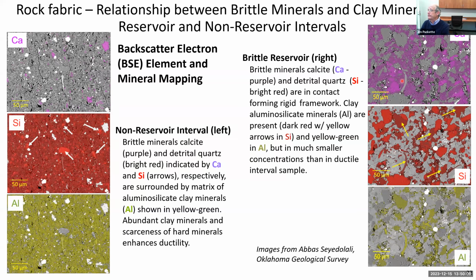Let's jump over to the brittle reservoir images on the right. And let's start down at the bottom with our aluminum. And you can see there's just a lot less aluminum in this reservoir sample. And in this middle image, again, we have bright red quartz, and you can see that some of these quartz grains are touching, which is always good. And when we go up to the calcium, we see a lot more calcium in here. So there's probably a lot more calcite cement in between these detrital quartz grains. And we're giving this rock rigidity. We're making this rock more brittle.